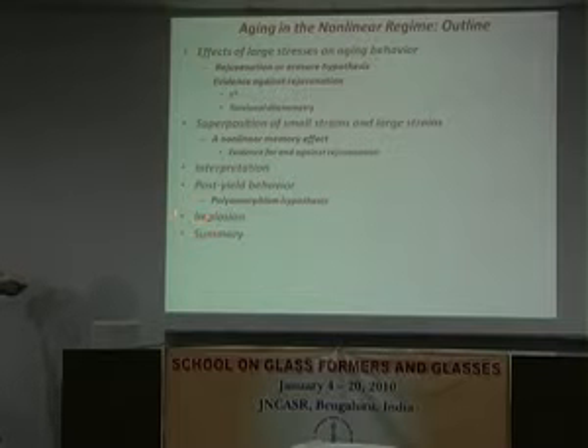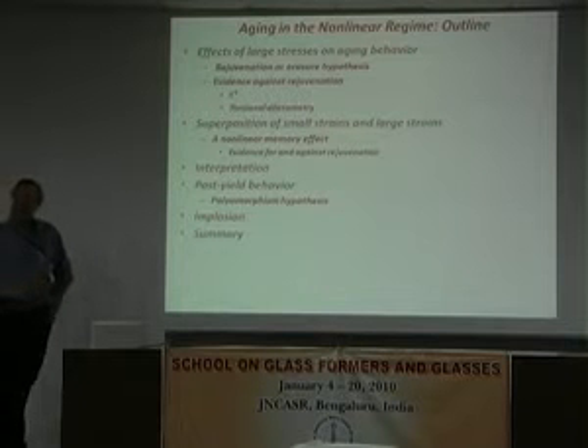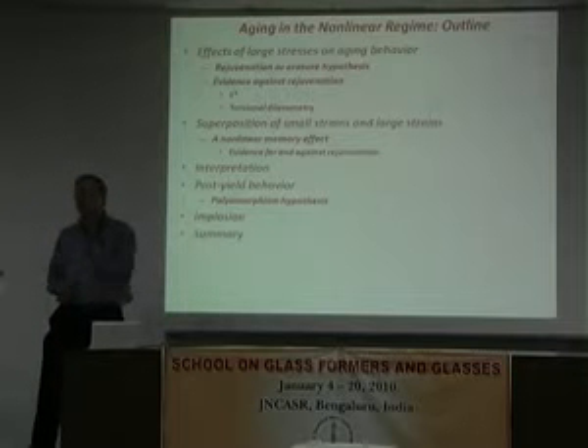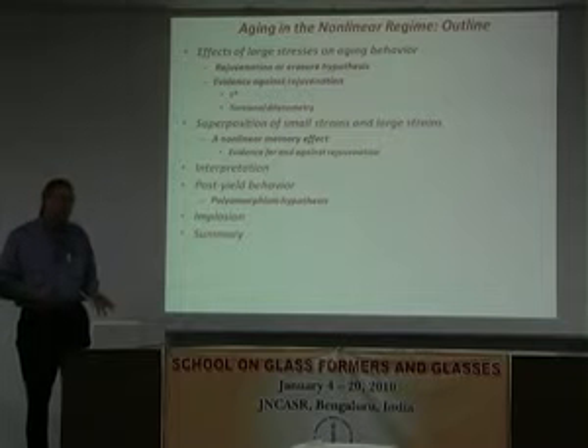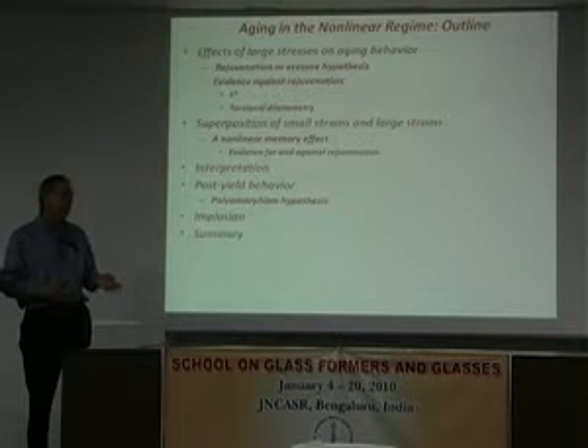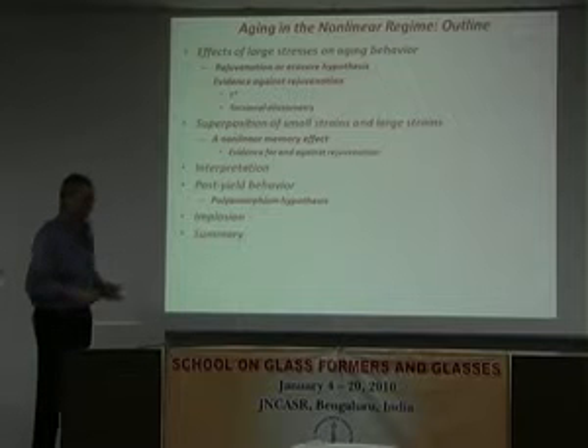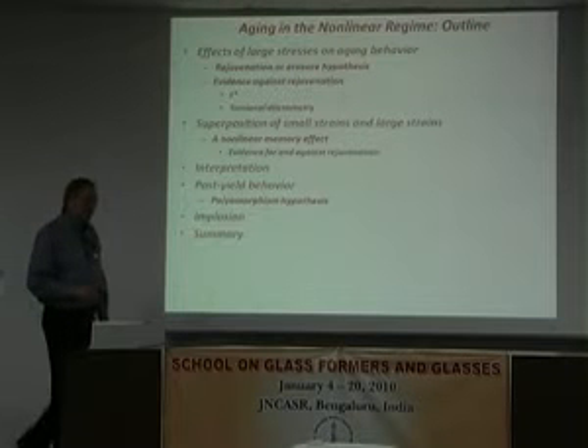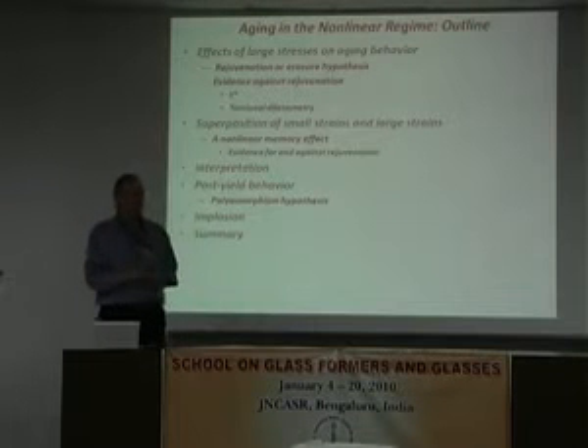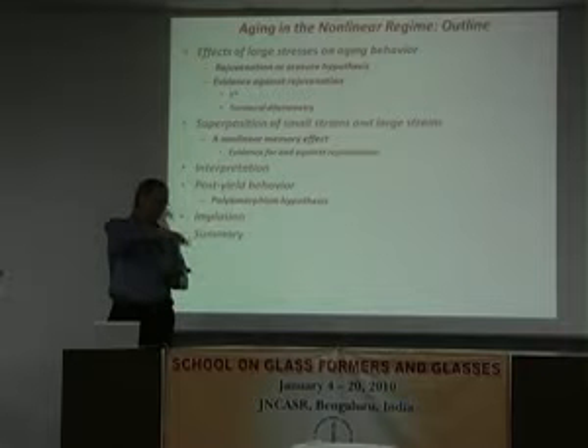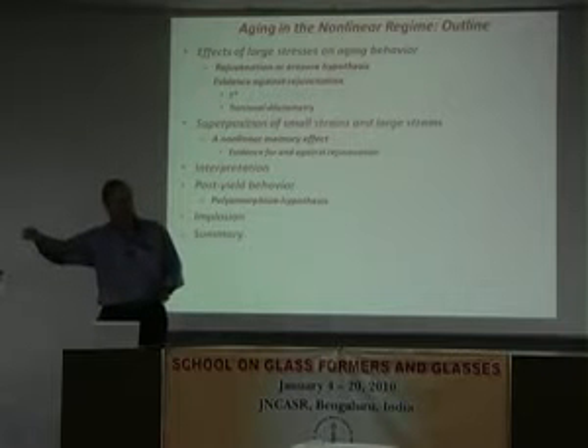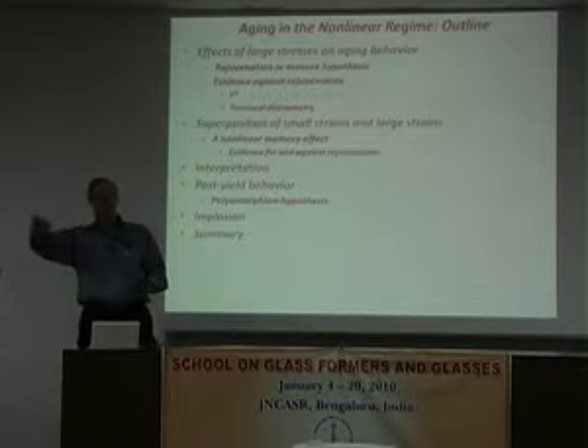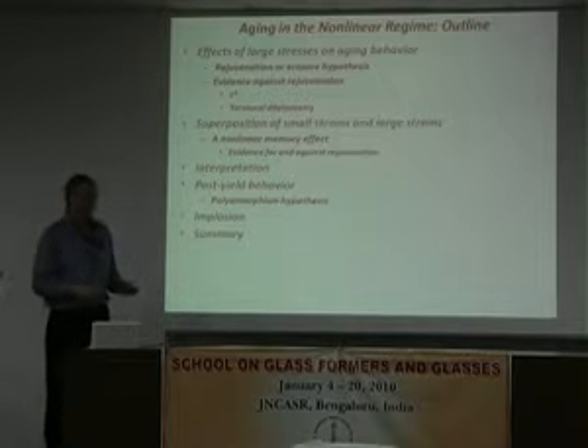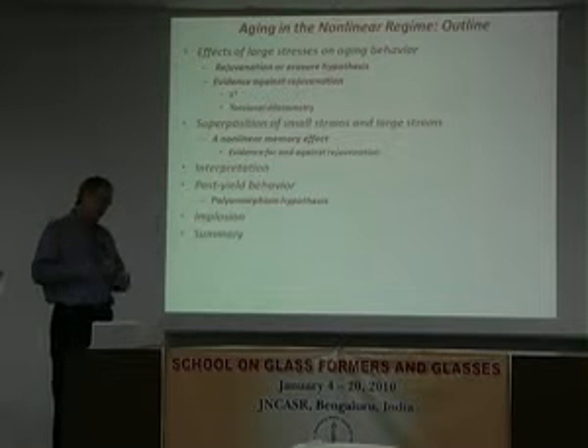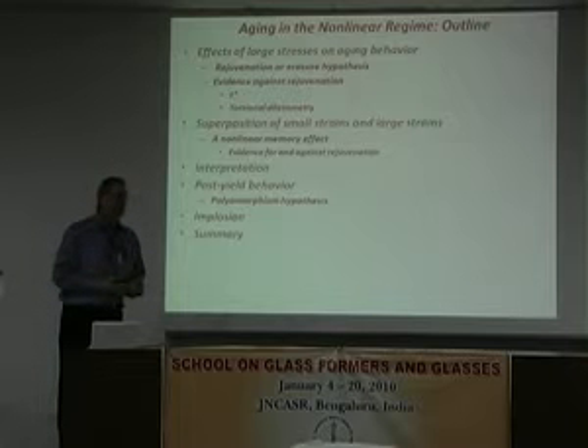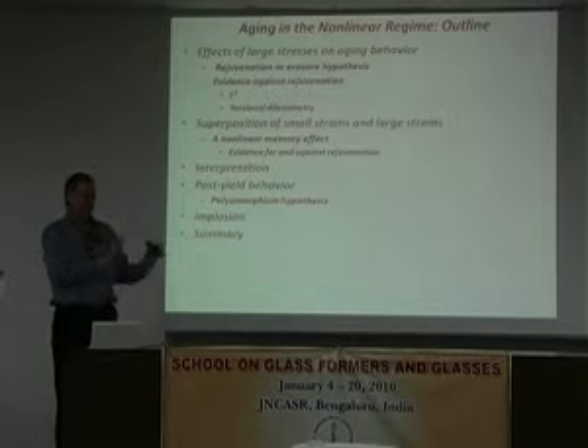And then I'm also going to give some evidence of some interesting results, if I have time, that have to do with post-yield behavior. Because I really have tried to do my work generally below the yield point, because when you go above the yield point, it's way too complicated. The yield point is generally where, when you do a stress-strain curve, it goes up and does something like that. It goes to a maximum in the true stress generally, and sometimes it's associated with shear banding and other things that I just didn't want to deal with.